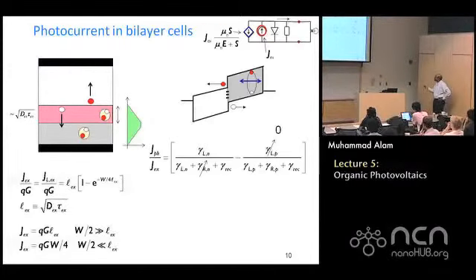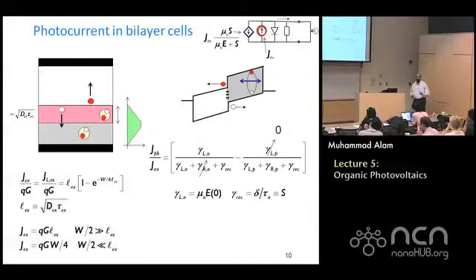Now, when this one comes out, what is the flux? Mu times E naught. E naught is the electric field here. That is the flux that is going to come out. No barrier in front of it. If you use the electric field, it's just going to slide down the hill and essentially be collected. On the other hand, if you have gamma recombination, this is a simpler expression. It simply says it depends on the recombination time constant associated with it. And if you have a lot of traps, the time constant will be low, and so that will be your recombination rate. You can put it in.